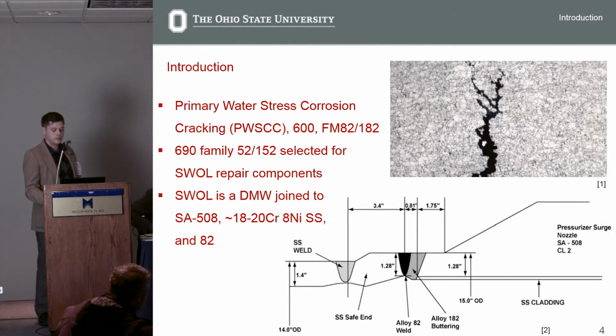So as I was saying, the filler metal 82 or 182 butt weld was insufficient to resist stress corrosion cracking in this weldment, which is very bad because this is primary water. It's never supposed to see the light of day again, and we want to keep it inside the pressurized vessel.